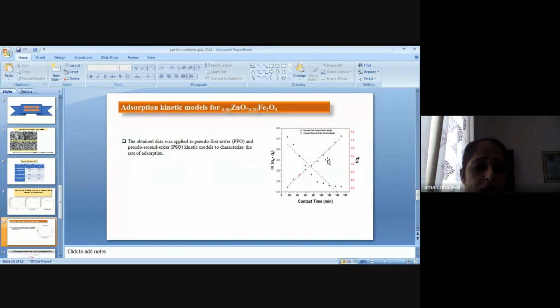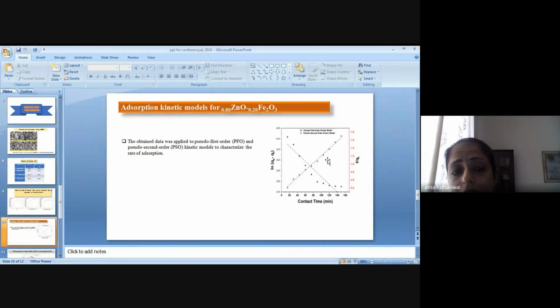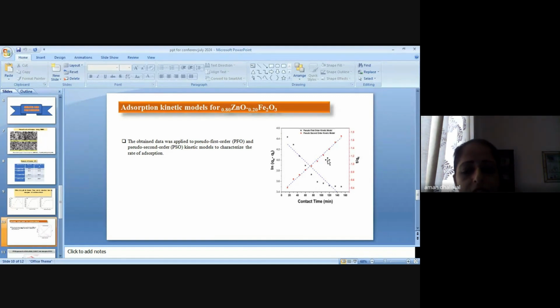After that, these are the adsorption kinetic models for the zinc, for these prepared nano adsorbents. The obtained data was applied to the pseudo first order and the pseudo second order kinetic models to characterize the adsorption rate. The pseudo second order kinetic model depicts the chemisorption process that involves chemical interactions with the binding sites on the adsorbent surface. Whereas the pseudo first order kinetic model shows the physisorption characteristics of adsorption.